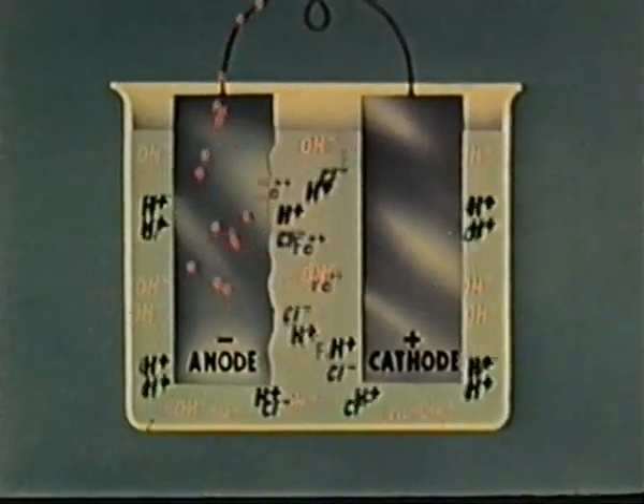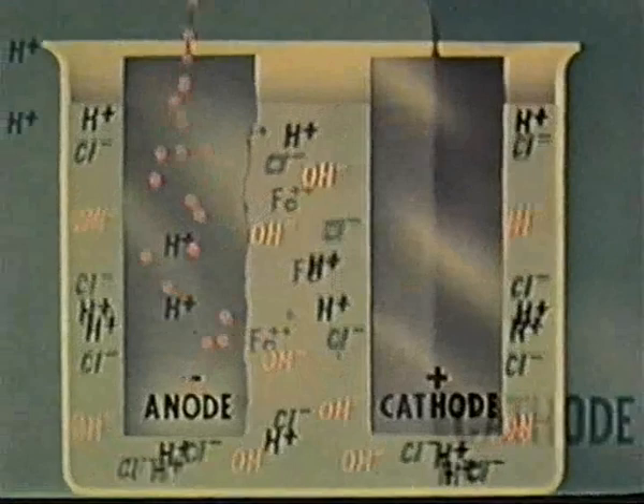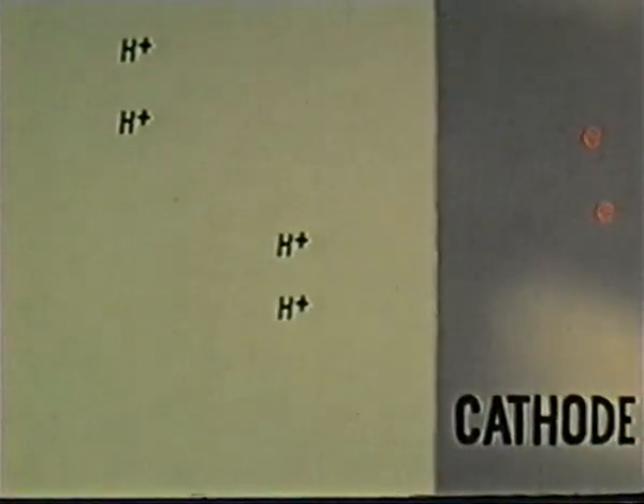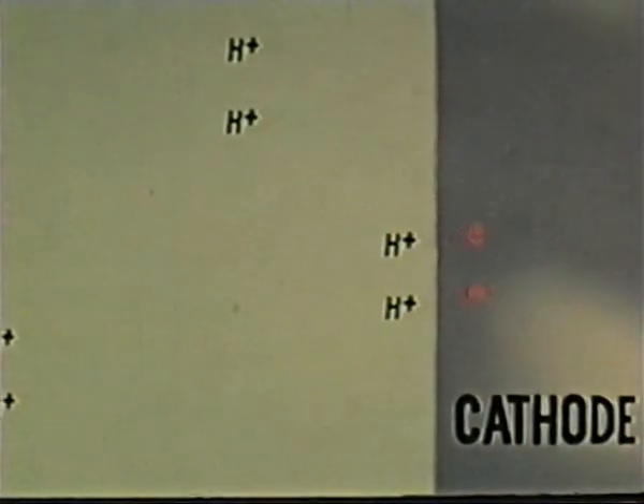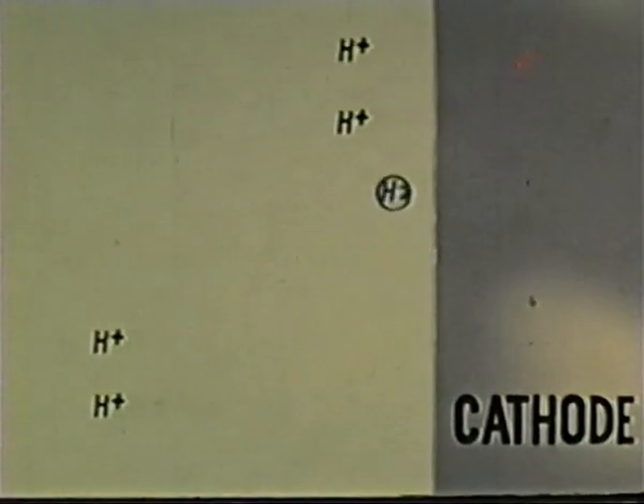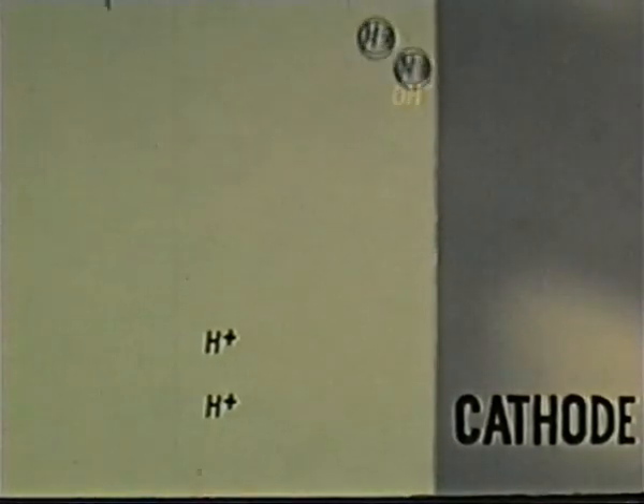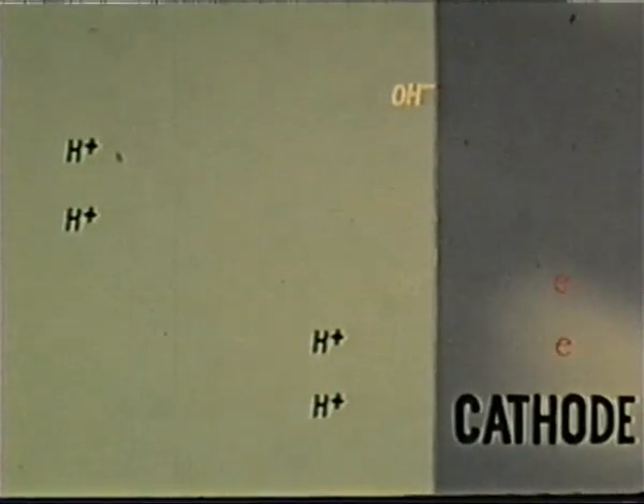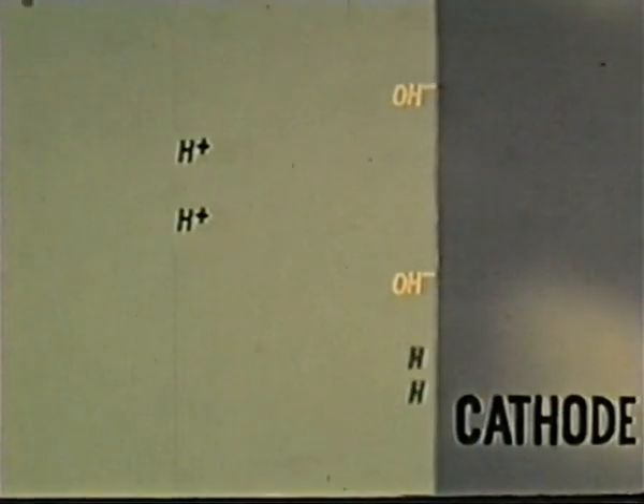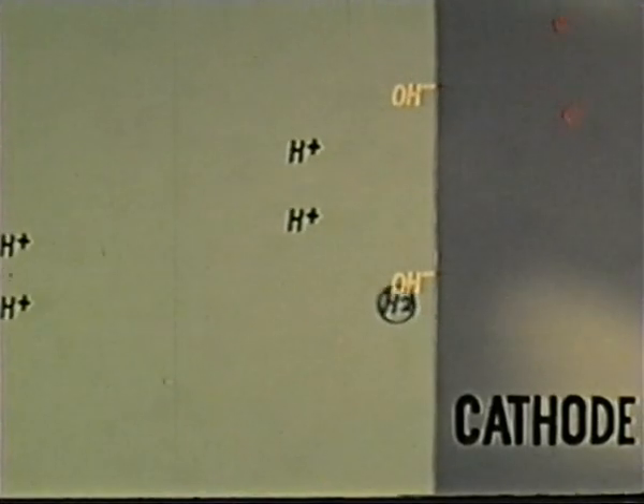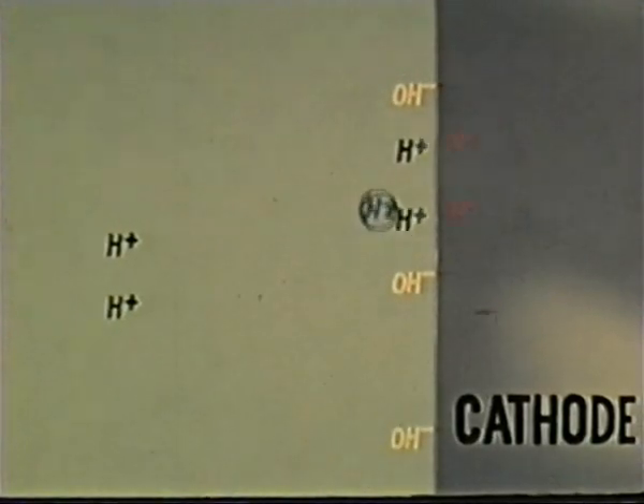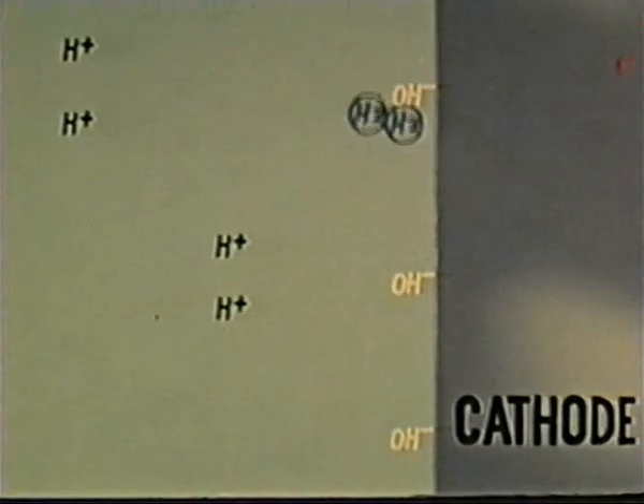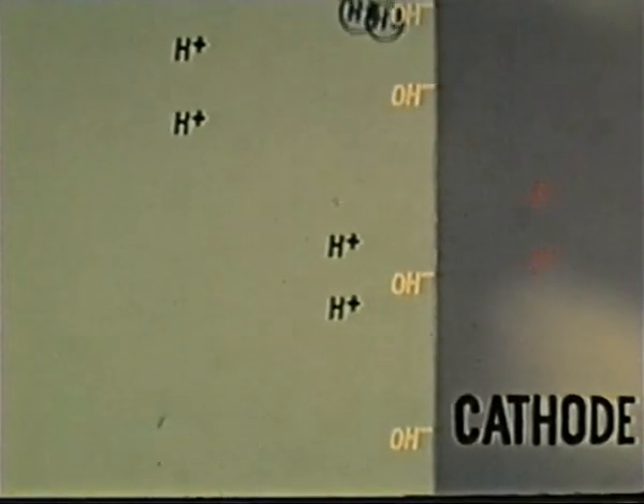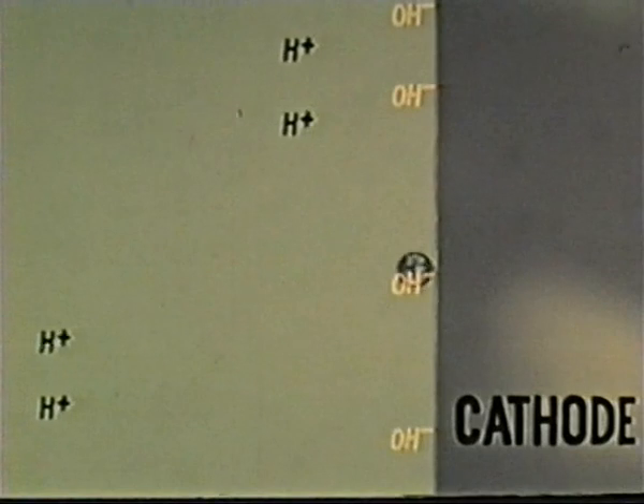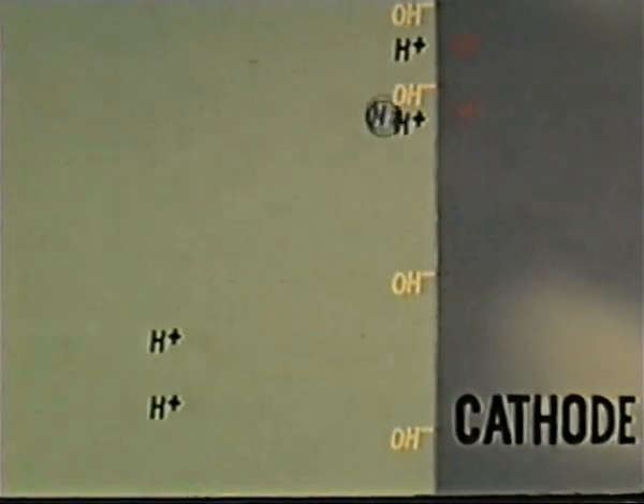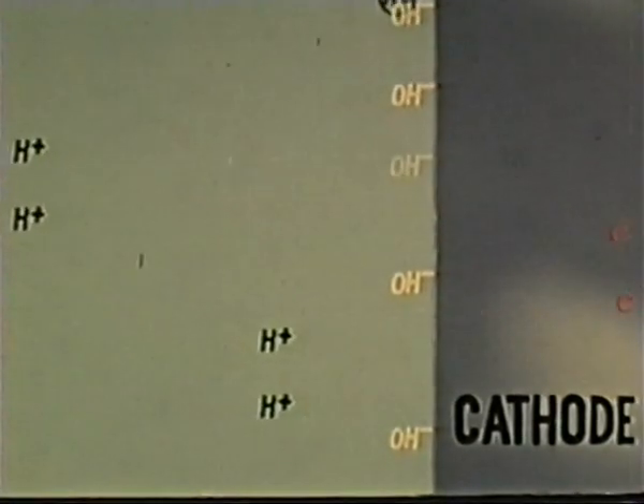As you can see, the electrons reaching the surface of the cathode through the metal have been meeting and neutralizing some positively charged hydrogen ions which have arrived at the same surface through the electrolyte. In losing their charge, the positive ions become neutral atoms again and may combine to form molecules of hydrogen gas. The reduction of hydrogen ions results in the accumulation of a relatively high concentration of OH- ions, which are left behind to increase the alkalinity at the cathode or make the solution less acid here.